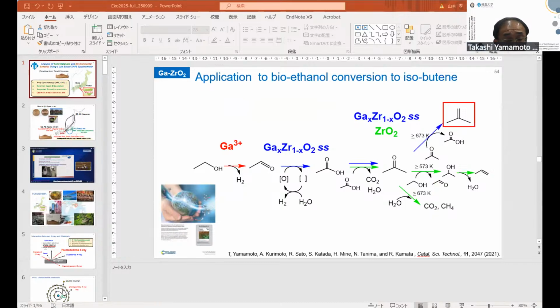Today I don't talk about this in detail, but in the presence of water vapor at 40%, this catalyst promotes isobutene formation, and we investigated the reaction pathways and active sites, the dehydrogenation and the solid solution, like this.